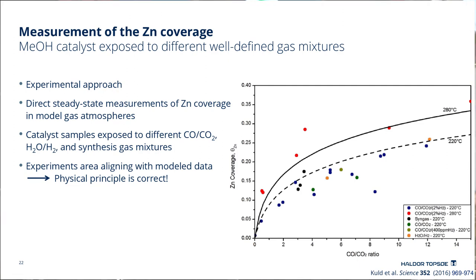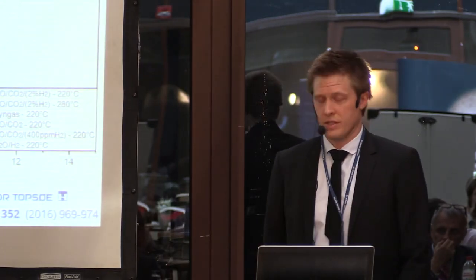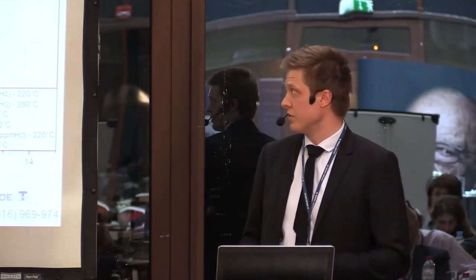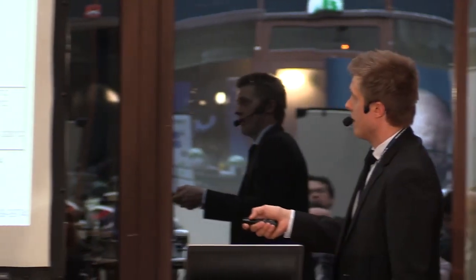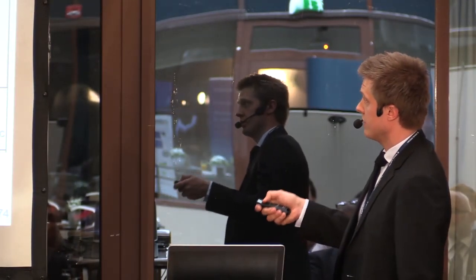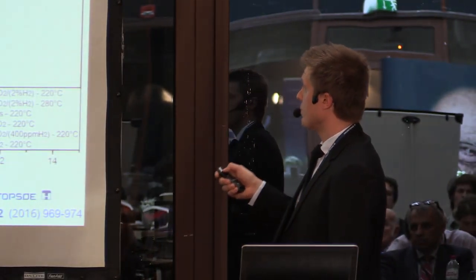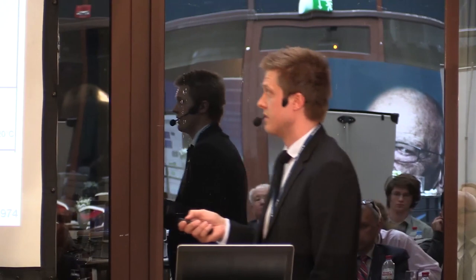The solid line and the dashed line is the model data from before for two different temperatures. And all the spheres are the experimental values where the catalyst system has been exposed to different gas environments with different CO and CO2 ratios, but also hydrogen and water has been used, and also real synthesis gas. If we look at the 220 case here, and you don't consider the red dots, then you can really see that all the experimental values are aligning very nicely with the model. So this really tells us that the physical principle behind this model is in fact correct.